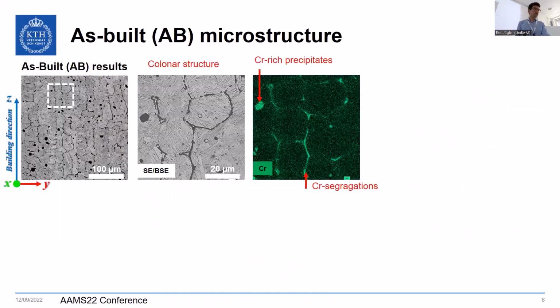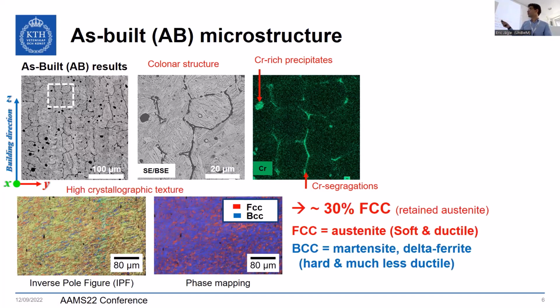So first of all, let's take a look at the as-built condition. As printed, you have a kind of columnar structure; the building direction is the vertical direction. You have some cells inside. You can see that at the boundaries of these cells, you have chromium segregation. You have some precipitates as well. In terms of crystallographic microstructure, you have quite a high crystallographic texture. This is EBSD imaging for inverse pole figure and phase mapping.